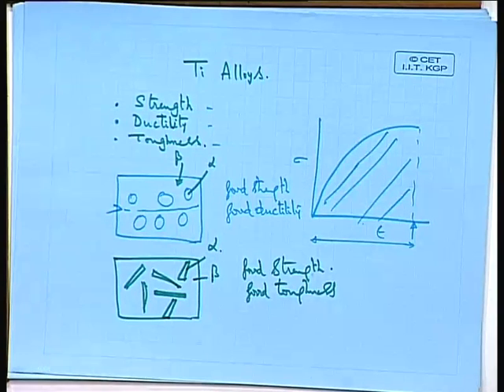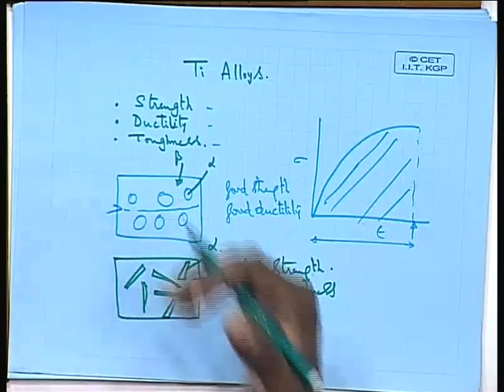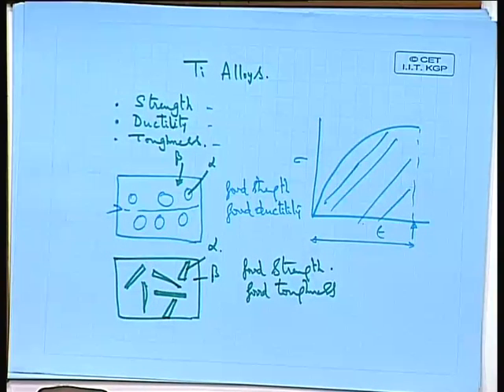So this is something which people knew quite before, and in titanium based alloys they try to see how we can achieve a combination of these two. The easy way to say is try to have both types of particles. The question is how to have it. So what people try to do is, we know that the morphology of the second phase depends on the way we do the heat treatment, and particularly it depends on the temperature at which the precipitate comes out.